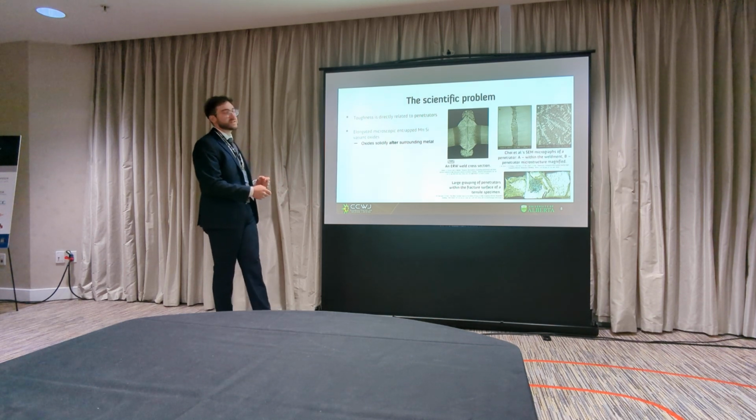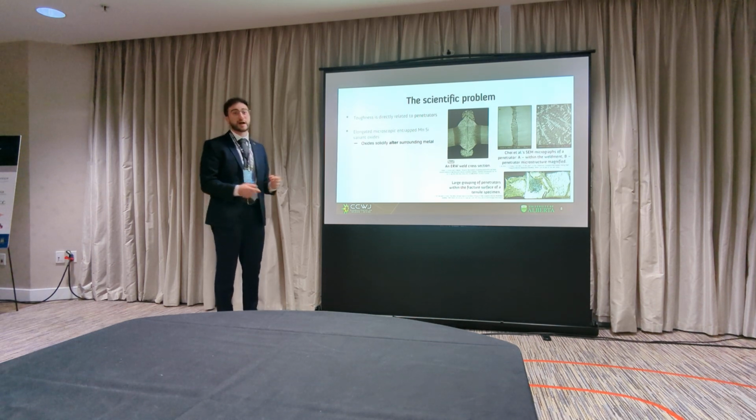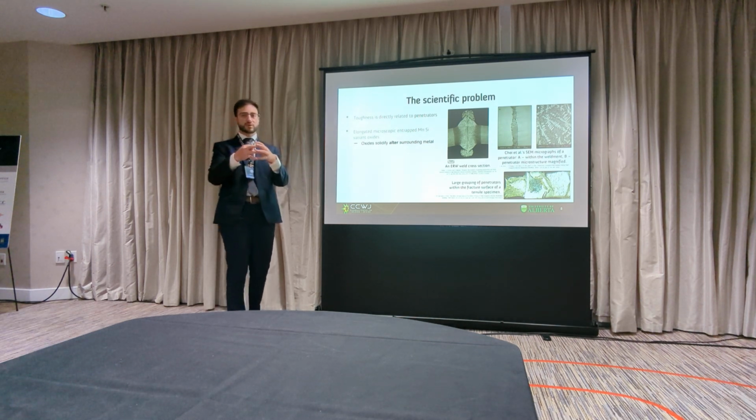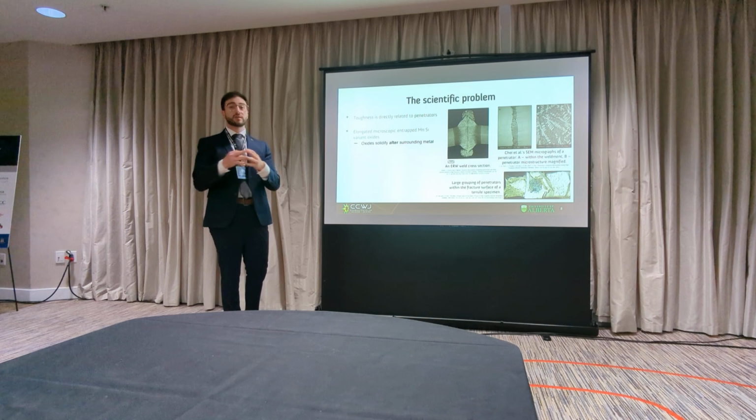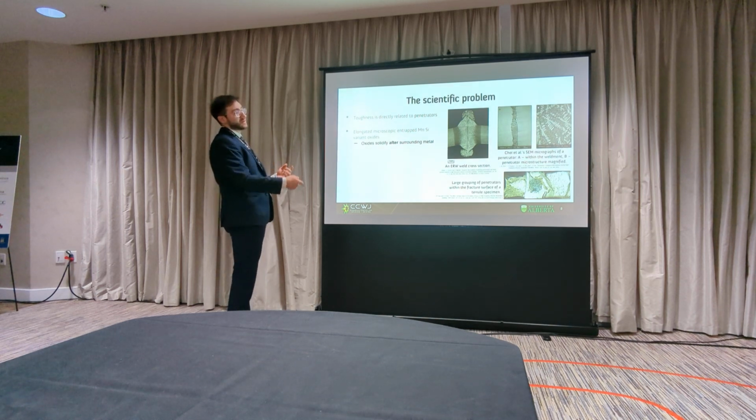And because they're a manganese silicon variant, they actually solidify after the surrounding metal. So after the steel's been joined, the metallurgical bond's been made, they're still liquid. And there's evidence of this just by these micrographs here.